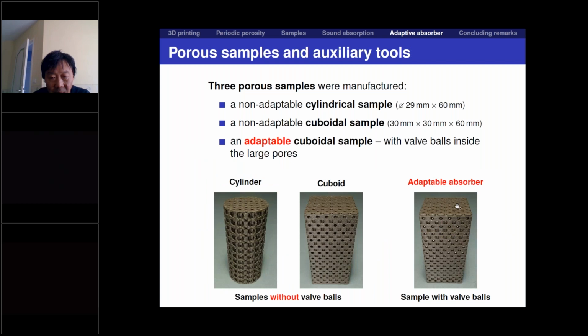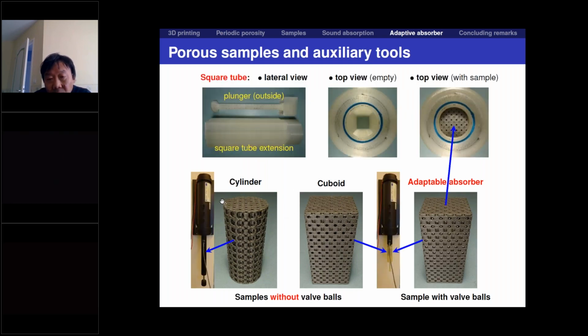All the three samples, the sample with the valve balls, without valve balls, and the one which is circular, or cylindrical, these are cuboidal. And we measured them in the metal tube with circular cross-section, and we also 3D printed a square tube for these cuboidal samples. And Camille paid a lot of attention to fit it well to our impedance tube.